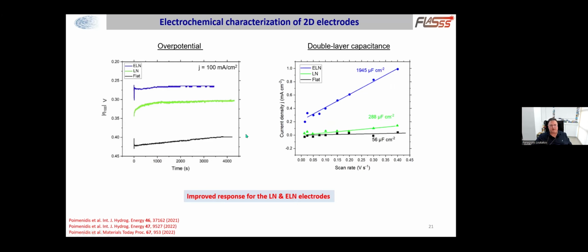Also, a very important observation is when looking at the overpotential performance at a stable current. We see that for the nanostructured electrodes, the overpotential is decreased. And this is very significant because the overpotential is basically a number that characterizes the performance of the whole electrolyzer. So the lower the value of the overpotential, the better the performance of the electrolyzer, because the overpotential is essentially the excess potential that one has to apply above the value that is thermodynamically expected in order to start the hydrogen producing process. So the less excess voltage we need to apply, the better the performance of the electrolyzer.